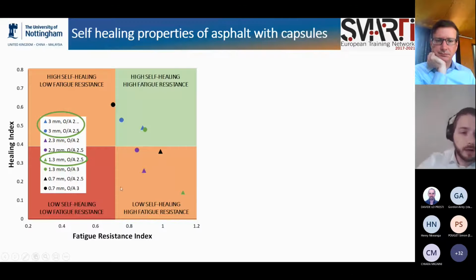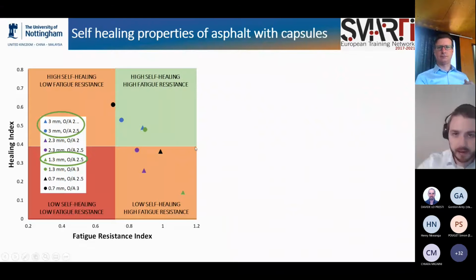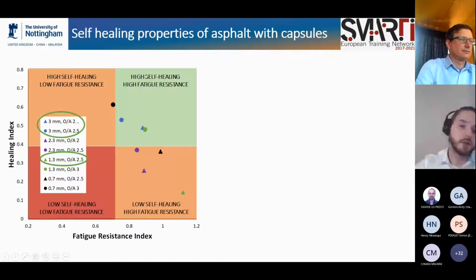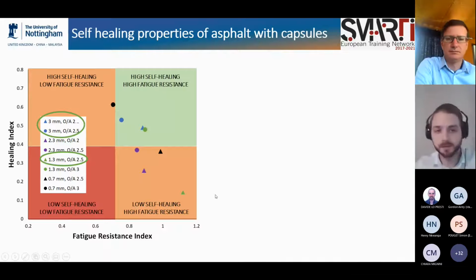So basically we created this graph, where you can see the healing index and the fatigue resistance index, and this green square marks the capsules where we got an improvement in the life of the asphalt of more than 15%. And this one in orange, we got an improvement, but it was lower than 15%. We just wanted to divide it like that. But none of the capsules gave us a bad result or worsened the lifespan of the asphalt.